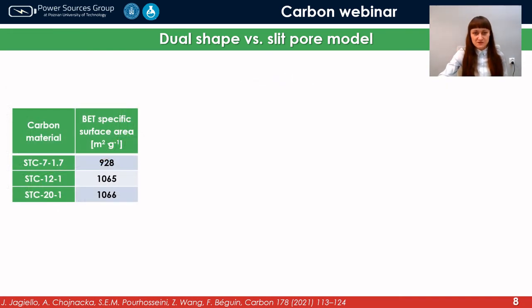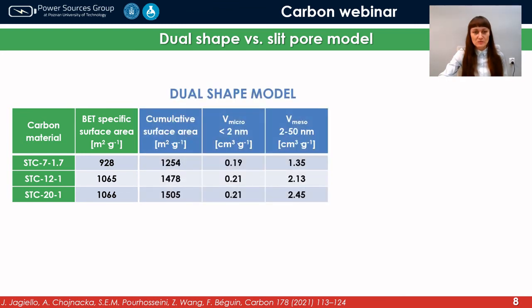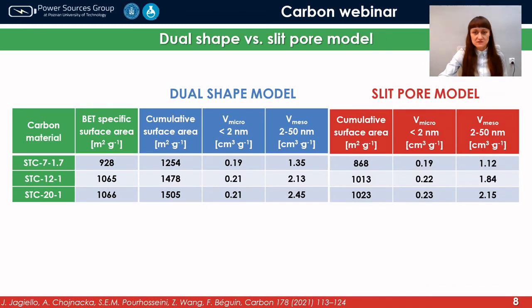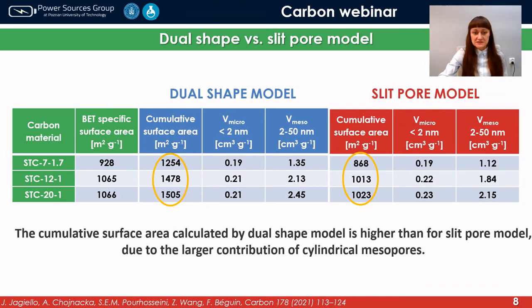To compare the dual shape model with the slit pore model more deeply, we compare the cumulative surface area and also volume of the micro and mesopores obtained from the dual shape model and the slit pore model. As you can easily see, the cumulative surface area calculated by the dual model is much higher than that calculated by the slit pore model, due to the larger contribution of cylindrical mesopores.